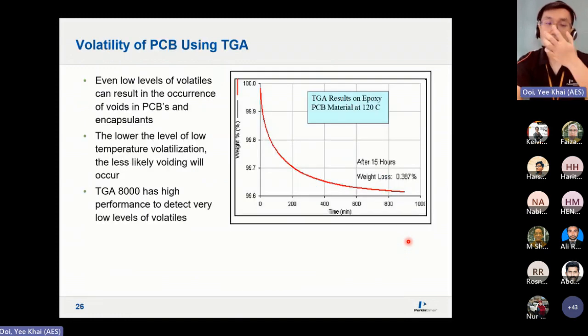So this is another one where they use TGA to check what is the solvent deposition onto the PCB, so printed circuit board, okay, in your semicon industry. So they can't afford any volatiles deposition onto the PCB because this will cause voids and malfunction. Okay, so the way they do this is they hold isothermal at 120 degrees C for 15 hours and monitor what is the weight loss. This represents the residual solvent that's deposited onto a PCB, and there is a threshold limit or acceptance limit. If there's too much, it means the QA/QC has already failed.